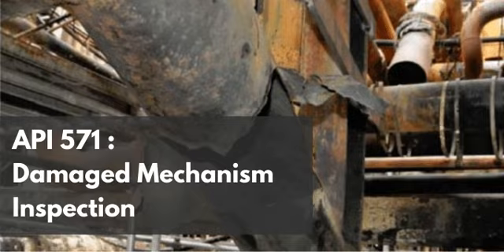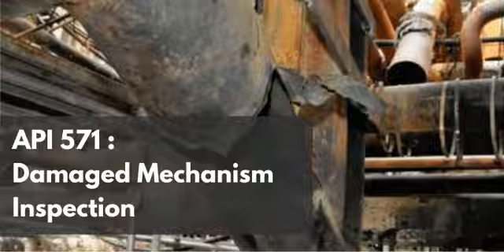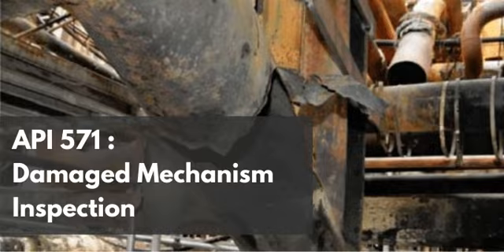Now, for the new carbon atoms out in the gas stream to reach the deeper, unaffected layers of the steel wall, they have to navigate and push their way through that already saturated, highly congested outer layer of thick carbides. Oh, I see. So that saturated outer layer begins to act as a slight bottleneck, physically slowing down the overall rate of diffusion deeper into the tube wall. So the deeper it goes, the harder it is for the carbon to keep traveling.